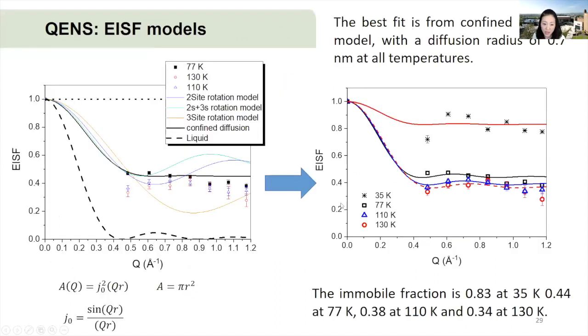The shape of the EISF can also be explained by models. I tried different models and found the best fit is the confined diffusion model with a diffusion radius of 0.7 nanometer at all temperatures, and that is in good agreement with our previous study. So hydrogen is confined and solidified inside the pores with a pore size of 0.7 nanometer. All of this is consistent. The immobile fraction is 80% at 35 Kelvin, reduced to 40% at 77 K, and continues to reduce as temperature increases.